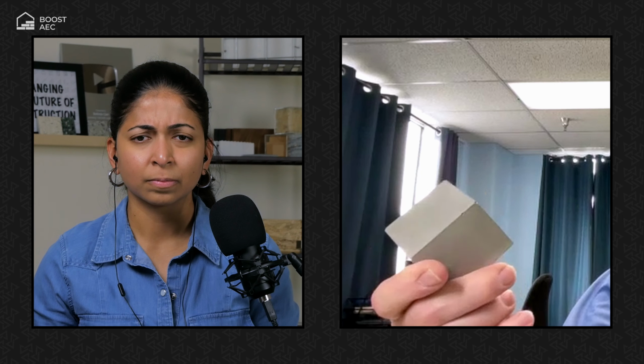But this technology, the Roman cement, we use as a coating. We also have some Roman cement repair material, and you can see what that looks like here. It's extremely dense. Again, it's a dense form of liquid granite is what it is. Is that pure Roman cement, or the material that you've made? It's not a coating or anything.